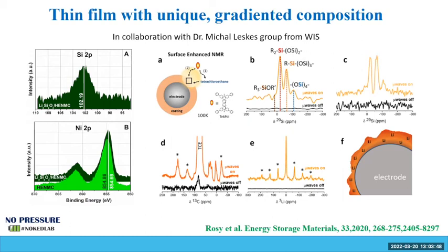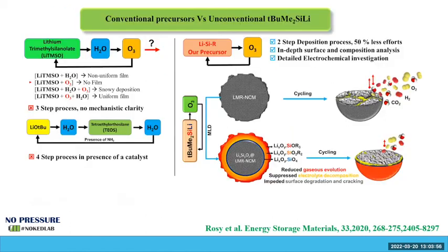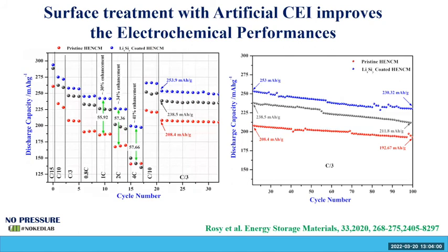And this is very desirable for electrolyte solutions in a battery, because now the wetting of the electrode should also be improved if there are organic residuals on the surface. And we could detect it also with the electrochemistry. So if I showed you before that this is the alumina base, when we go to 4C, we do not see improvement. This was a 41% improvement when we are coating it with our lithium silicate.